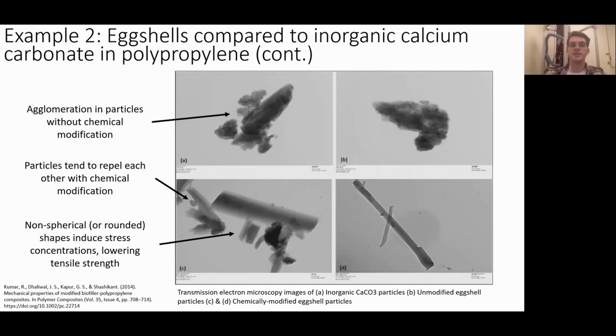So in images C and D here, these are the eggshell particles that incorporate a chemical modification. And what we can see here is that the particles tend to repel each other, which tells us that we're getting less agglomeration in our final composite, which is going to give us better dispersion and a higher tensile strength. Something interesting to note here, though, is that the particle shapes are all slightly different, which again, going back to that shape factor from Guth's model, is going to give us a different tensile strength regardless of the chemical modification we put on these particles.